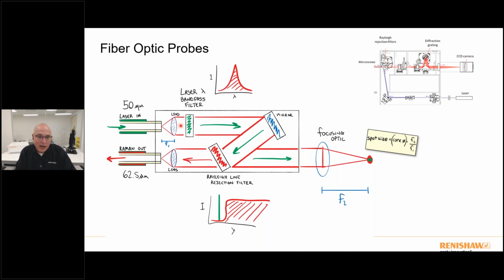When I take these fiber optics, the first thing I'm going to do is collimate the light coming out with some sort of lens and put it into this infinity space where I can introduce some filters. Now, the first thing you want in a fiber optic probe is a laser bandpass filter, pretty similar to what we have in our Raman spectrometer when we're coupling this to a microscope. The use here is that when you put a laser beam into a fiber optic, on the output of that fiber optic you're going to get the laser coming out of it, but you're also going to get the Raman spectrum of the fiber. So it's important to put a bandpass filter in there so that you're only seeing the laser beam illuminating your sample and not the Raman spectrum of the fiber optic, which would complicate your results. So we'll use a mirror to deliver light towards a Rayleigh line rejection filter, which again delivers the laser beam to the sample.